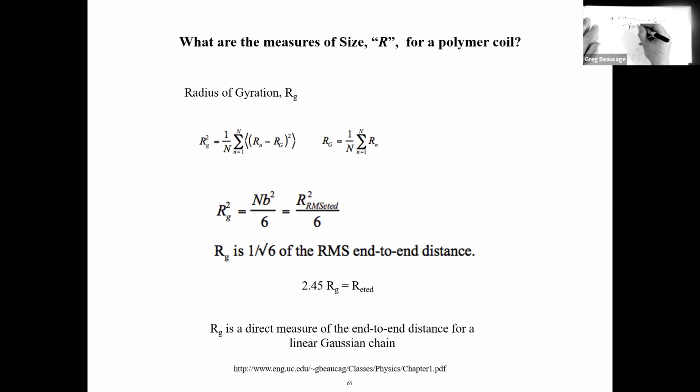So it's a polydisperse system, and you're going to get RG from scattering, which is e to the minus q squared RG squared over 3, which is approximately 1 minus q squared RG squared over 3.